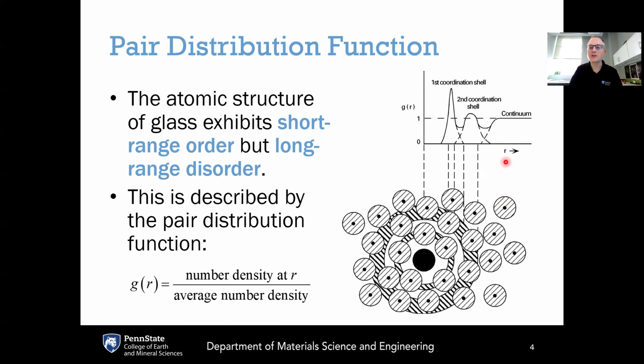And then as we increase r, moving to the right on this plot, increasing r means that we are expanding out radially from the central atom. So r equals 0 is at the exact center of this atom, and as you expand out radially, you're creating these concentric shells that are expanding out, where the center is always at the central atom here, but the radius of these shells is becoming larger and larger. So these dashed shells, the larger circle as it's expanding shown here, correspond to larger and larger values of r, where r is the radius of those particular shells.